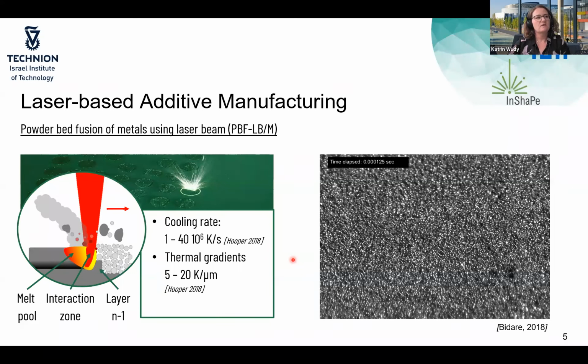Everything I showed to you before was only for one single weld line. But in additive manufacturing, you put a lot of these lines, these scan passes, beside each other. So one scan pass would be in this direction. And what you then see is, of course, an overlap between your different scan passes. The aim is always to have an overlap of around 30%. If the overlap is too low, so the distance between your different passes is too high, then you are not really connecting these passes with each other.